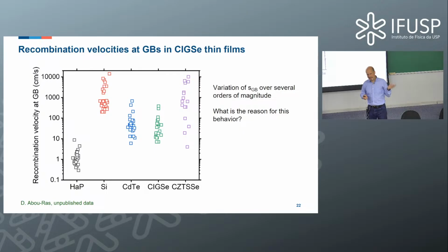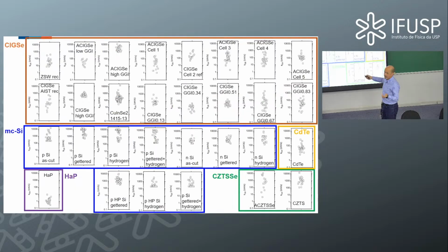And if you say, okay, this is quite nice, but it's not a very good statistics, this is what we have measured so far. And we have measured actually a few more, yes? So what you look at is about 30 different measurements. All the axes are the same. They go from 0.1 to 20,000, okay? And you can see the behavior for all these samples here: this is copper indium gallium diselenide, this is microcrystalline silicon, this is halide perovskite, this is kesterite material also used for solar cells, this is cadmium telluride. You see the behavior is always the same, goes over several orders of magnitude, right? And this calls, of course, for a common model. It's quite evident that something must be very similar for all these cases if the recombination velocity always behaves quite similar. So what actually is behind this?